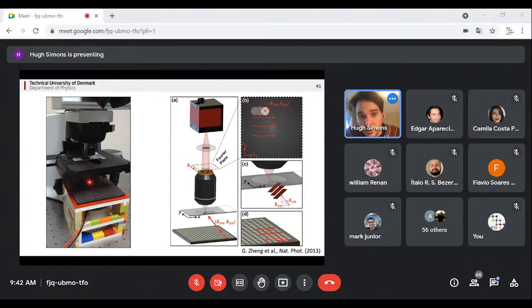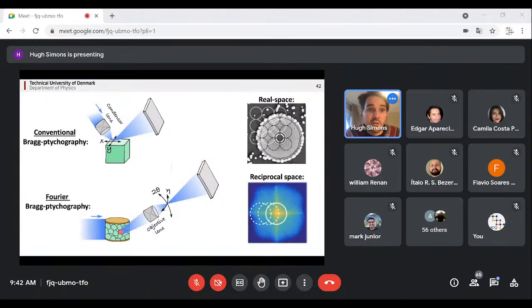And so this is something we've been working on a lot in the last few years. That's to introduce something called Fourier-Bragg ptychography. The idea is that we simply move our objective lens, which is what we need to do anyway in order to measure strain and misorientation. But by using an iterative process, we can reconstruct both the amplitude and the phase. With this, we merge these techniques like Bragg coherent diffraction imaging, or Bragg ptychography as it's often called, and use many of their techniques as well to improve our approaches here.